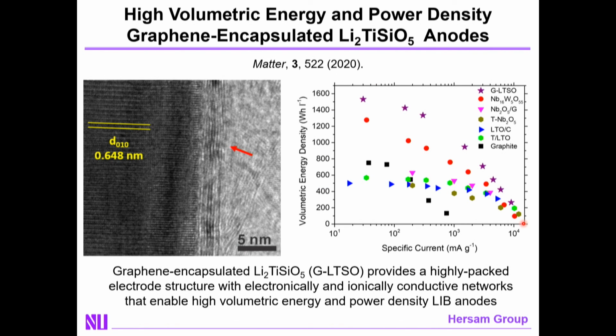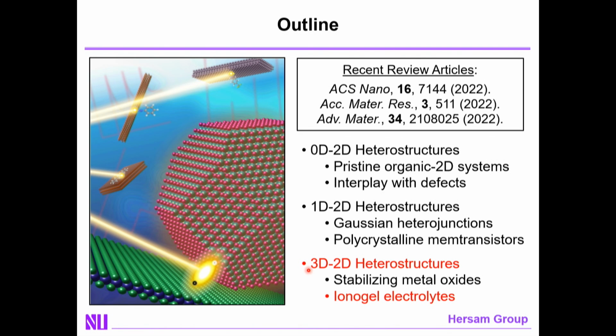I will note for completeness that this also is applicable to the anode side of the battery. If you have an oxide-based anode like lithium titanium silicon oxide, you can again get the beautiful graphene conformal coating. In this case, it enhances the conductivity and therefore the rate performance on the anode side of the battery. The point is that this coating works well on both the anode and the cathode side, which then leaves one final part of the battery left, and that is the electrolyte.